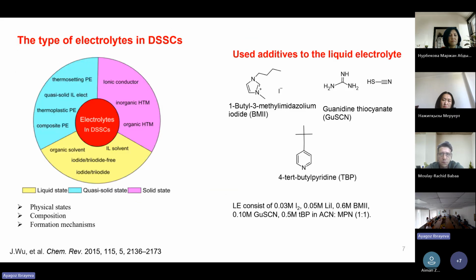As you can see in the working principle of the dye-sensitized solar cell, liquid electrolyte interacts with all parts, such as counter electrodes and photoanodes. That's why it is important to improve their performance and avoid leakage and evaporation. According to the physical state, composition and formation, we can divide electrolytes into three broad types. They are liquid, solid state, and quasi-solid state electrolytes. In our research, we used some additives, which are given here: butyl-methyl imidazolium iodide, guanidine thiocyanate, and 4-tert-butylpyridine to enhance not only photovoltaic performance, but also to suppress recombination and for surface passivation.